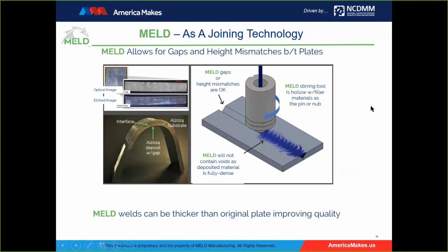Okay, again, based on the principles of friction stir welding, but now our pin is not solidly connected to the tool. It's our feedstock material coming out the bottom of the tool. And so we get zero tool wear, which is a joke because we are melding that pin, or our feedstock material, as the material to join the plates. And here's a couple of things we can do differently. You can have plate height mismatches. You don't have to have same height plates. You know, we can add different height mismatches.